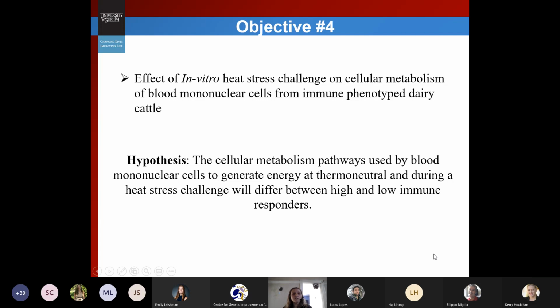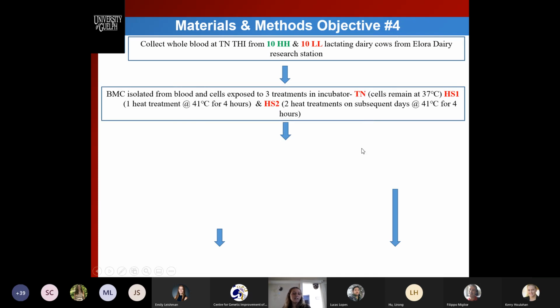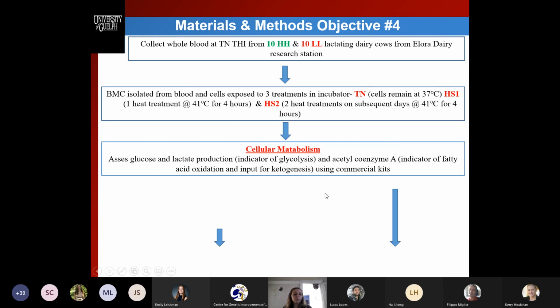So the objective for this study was to look at the effect of an in vitro heat stress challenge on cellular metabolism of blood mononuclear cells from immune phenotyped dairy cattle, with our hypothesis being that the cellular metabolism pathways used by blood mononuclear cells to generate energy at thermoneutral and during heat stress would differ between high and low immune responders. For this study, we collected whole blood at thermoneutral THI from 10 high and 10 low lactating cows at Elora Dairy. Then we isolated blood mononuclear cells from these cows and exposed them to the 3 heat treatments that I talked to you about previously in that first objective. And then we looked at different cellular metabolism outputs.